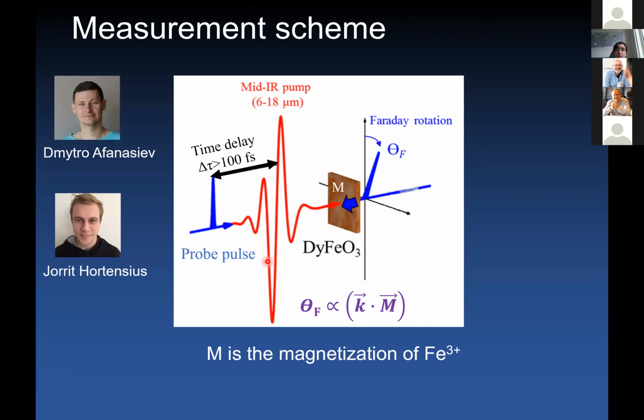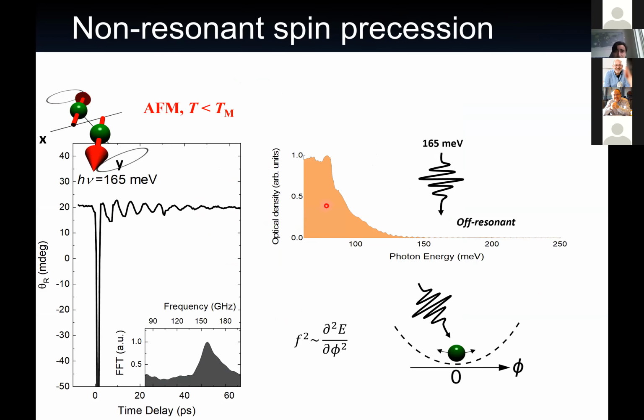We do this by a pump-probe scheme, where we probe the Faraday rotation. We send a probe pulse that has a controlled polarization of light. We measure the rotation of this polarization in the presence of a magnetic field, and by doing so, we are able to resolve the magnetization of the iron 3+ in this system. This is a function of time delay between pump and probe. The pump is tailored to either excite, or not, in resonance, the lattice modes.